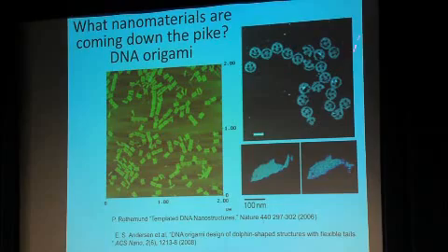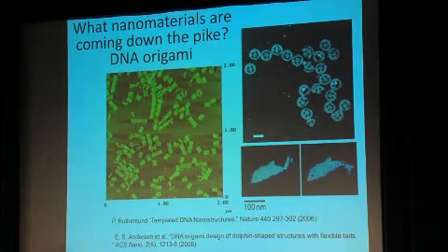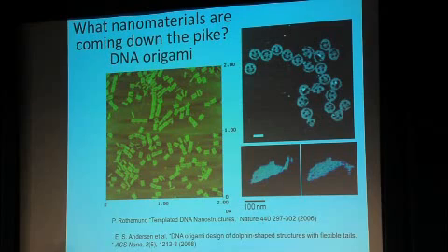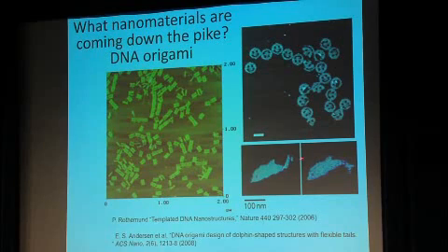And they're folded up to form different two-dimensional structures using a set of design rules, and also using auxiliary synthetic DNA fragments. Okay, so these are nanomaterials because the characteristic dimensions are certainly on the nanometer scale in terms of length and width, and also the thickness of these particles is only about 2 nanometers. So they're pretty close to being single molecular sheets.